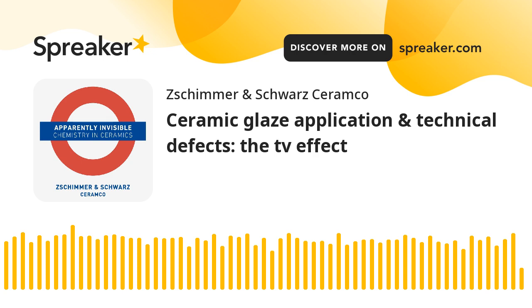The glaze, since it undergoes a high, and we could surely say too high, surface tension, tends to take a spherical shape, moving towards the outer parts of the tile in order to decrease the surface energy. But before we keep on going, we will be back later on to the spherical shape, I would like to give you a short definition of surface tension, even in this case by using a very simple and I hope not trivial language. Well, surface tension is the tendency of liquid surfaces at rest to shrink into the minimum surface area possible.